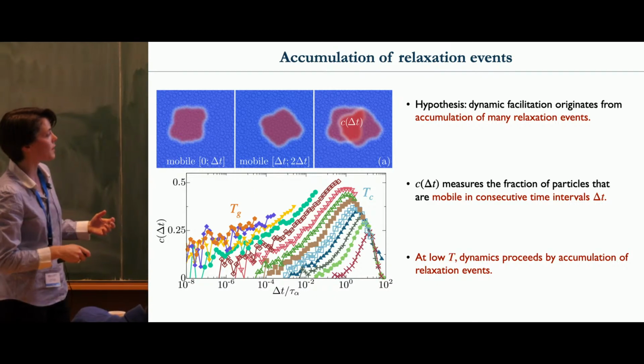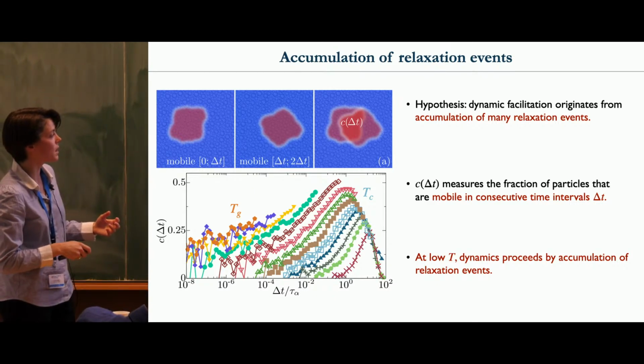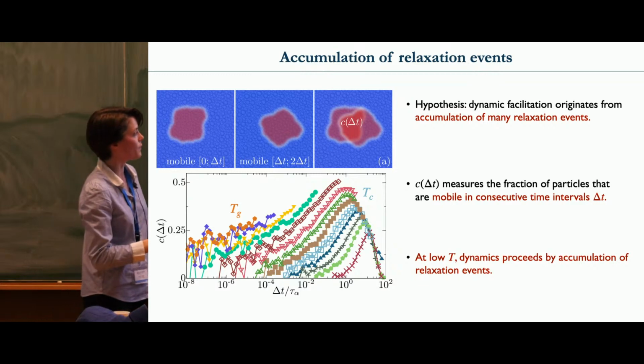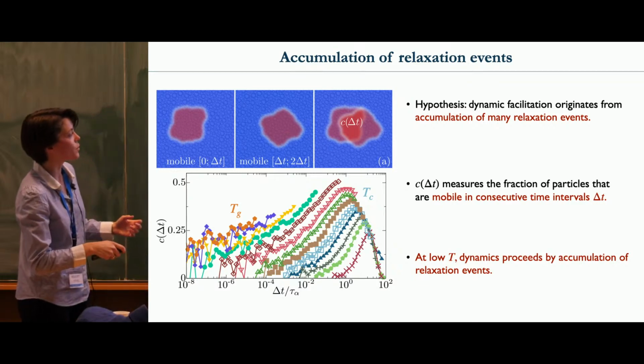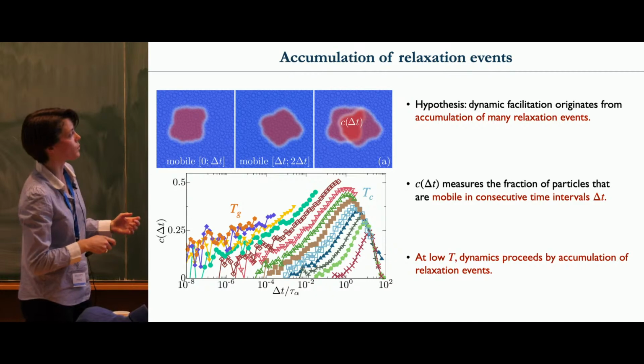And we do this measurement as a function of the time interval delta t, again scaled by tau alpha, for many temperatures, from high temperatures to low temperatures closer to TG.